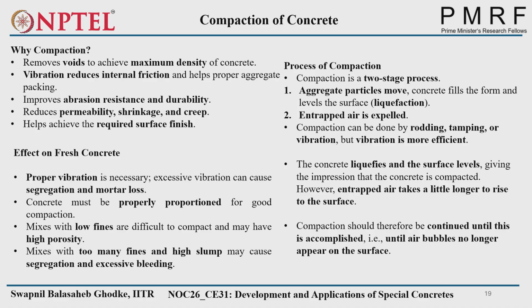Excessive vibration can cause segregation and mortar loss. Segregation means larger particles depart from the cement matrix or the fine concrete. Then concrete must be properly proportioned for good compaction. Mixes with low fines are difficult to compact and may have high porosity. Why difficult to compact? Low fines provide higher cohesiveness, and because of the higher cohesiveness, more energy is required to compact. With low fines, there is higher interlocking between the aggregates, and that will require more energy. And whatever low void space is available will not be filled fully. So that's why high porosity.